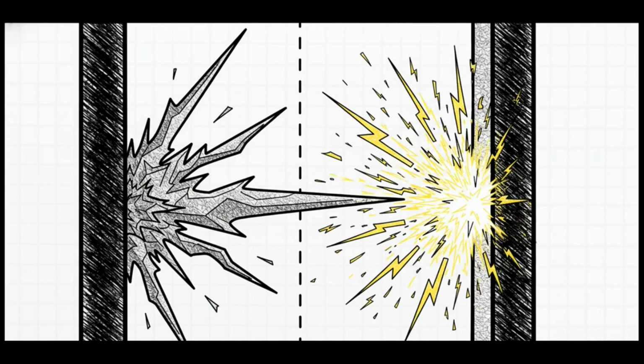The cascading effects of this lithium plating are devastating. It causes an immediate loss of active material and traps inactive lithium ions, leading to permanent capacity fade. In fact, operating aggressively in the cold results in roughly 4 times higher cycle life degradation. But wait, it gets worse.